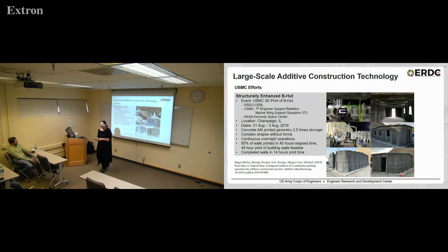A lot of people around the world, because they use mortars and paste, have to deal with a high slump material. And so if they put consecutive layers on consecutive layers of wet concrete, it eventually slumps off and it fails. With our material, when we print something that's as large as this, which is 16 foot by 32 foot by 9¼ foot tall, to print something that big in one layer, by the time we come around for that next layer, it's been about 4 minutes or so, and the material is set up just enough that it can support that next layer.